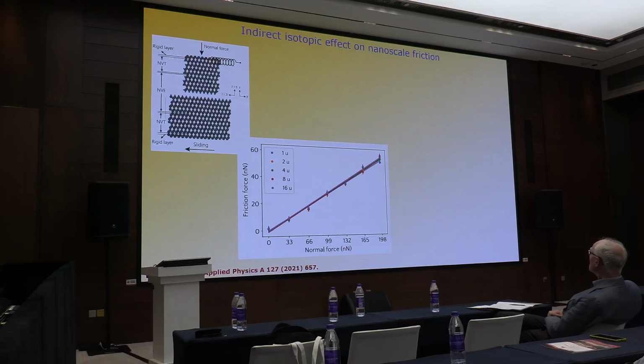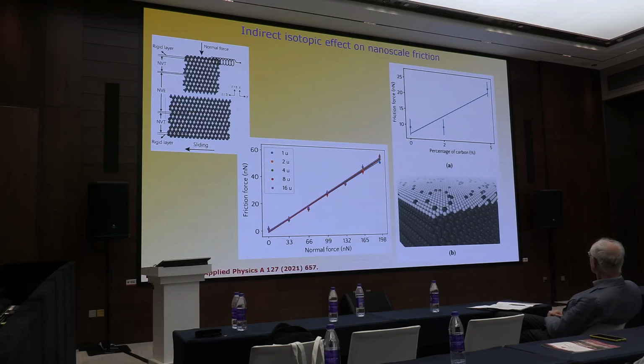This is good because, remember, tribology is very complex. This colleague simulated as well and arrived at the same result as Isabella, that the friction doesn't depend on the mass of the adsorbate, or there is no isotopic effect. But what happened? I remember the idea of Isabella: different quantities of hydrogen and deuterium on the surface. Maybe this is the most important point. Maybe we have to understand the structure of these surfaces, and what is the quantity of deuterium or hydrogen on the surface that interacts with the tip for the measurement.